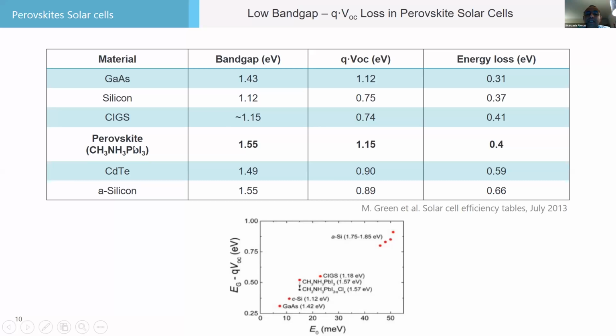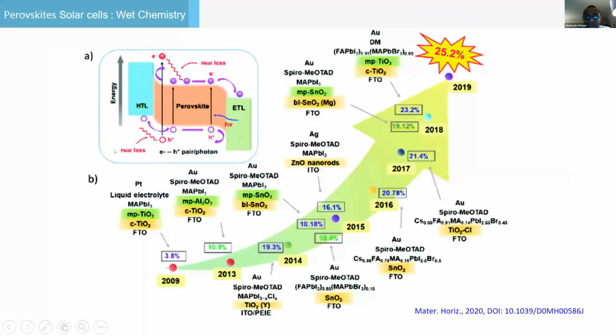If you take the standard methylammonium lead triiodide, it has a band gap of 1.55, and we can get a 1.15 VOC. So the loss is very small. Even some people have reported higher values and lower losses. You can go to 0.35 electron volt losses, very low. So this is another chart of how we make progress. This is a recent review article. You can follow from there if you're more interested.